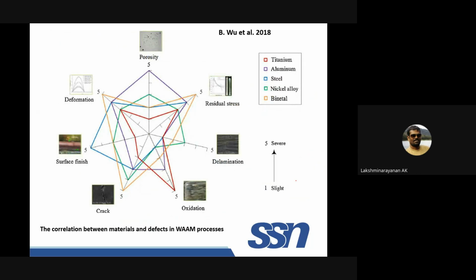Considering this, the author has beautifully constructed a radar plot of different materials and different defects. Just for reference, I have shared it here. Titanium, except for oxidation, everything is good or very low. Aluminum has a problem of porosity, which is bigger, because you see a 5-point rating there. For any bimetal, deformation is the issue. If you use steel, the surface finish is always a problem. Like that, you can just refer. Bimetal deformation is higher. There is a problem of cracks. The scale is given like this: one is slight and five is severe. From that you can try to understand.